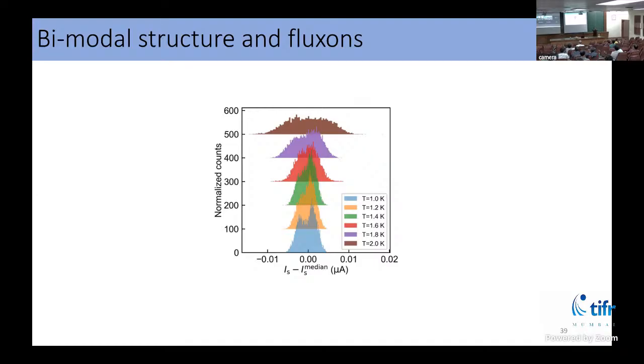So when I am actually sampling my 1 micron structure, I am sampling both these networks: one which has a vortex, because of which it has a lower switching current, and a network which does not have a vortex and has a higher switching current. So if I do this statistically enough number of times, I am sampling both. So that is actually the reason why there is a bimodality that is getting introduced.